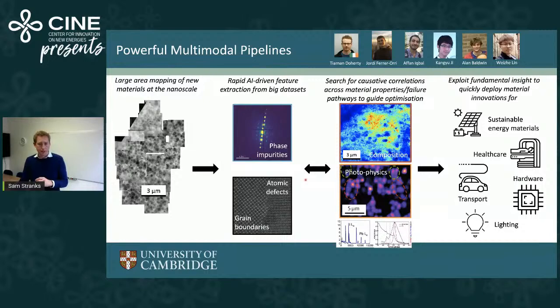And I want to finish with two slides, one to show where we're going with this and what the vision is with these multimodal measurements that we can now do. We've been showing them on perovskites, and we're now applying them to other materials and other perovskite families as well. This is where we look at much larger areas using scanning electron diffraction, for example, taking nanoscale images over bigger regions of the film, and using that to identify phases and construct phase maps of these materials, so I can very readily extract any phases that are there, any impurity phases as well, using algorithms to do that from extremely large data sets. That will be important. We can't do this manually, of course.